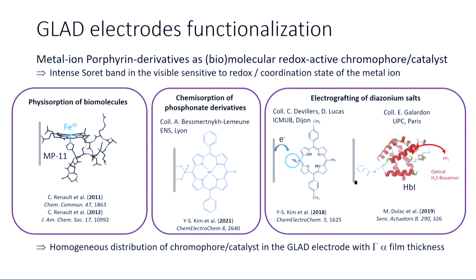So for the modification, you can either use simple physisorption of biomolecules thanks to multiple anchoring groups. You have satisfactory, let's say, stability. You can make something that is more stable with chemisorption of phosphonate derivatives. And you can also electrograft aryl diazonium salts to prepare these functionalized electrodes. And in my presentation here, I will mainly focus on these two porphyrins. One is microperoxidase 11, which is an iron porphyrin, and the other one is a manganese porphyrin.